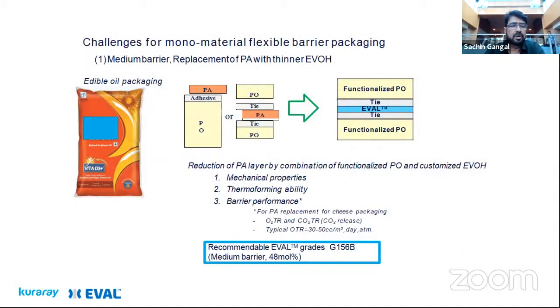Some applications we are working on is an edible oil packaging where nylon can be replaced. Yes, the mechanical properties of nylon could be taken care of by the new generation polyolefins, the metallocene polyolefins, and the EVOH can, of course, contribute to the barrier. If I understand, currently used structure for edible oil packaging is, I believe, 110 micron film with about 18 to 20 microns of nylon. Now that job can be easily done by 1 micron of EVOH. Yes, on some machines it's a challenge to produce 1 micron of EVOH in a 100 micron structure, but when you're talking about recycling and sustainability, maybe in future you will have edible oil pouches which are based on EVOH and which have replaced nylon. Next slide, please.